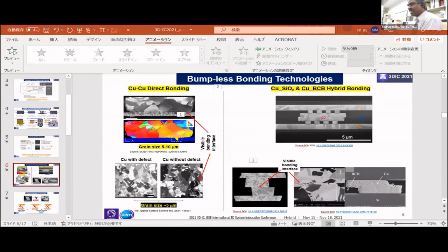These are again some of the things. As you can see, the bottom one is from some research group and the top one is using the nanotwin structure. They have got very good copper-copper bonding. But what I would like to say is, you can see the colored image. This is the bottom copper pad, and the other color is your copper micro bump. If you look carefully, you always end up with some copper interface. Why? Your bottom copper pad has one copper grain orientation, whereas your top copper bump has a different, polycrystalline orientation.